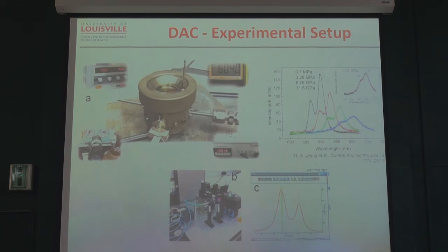Yeah, so this is the experimental setup we have in our lab. So this is a diamond anvil cell. To measure the pressure, you have to use something called a ruby crystal. Ruby has the photoluminescence peak. Under pressure that peak shifts, so from that you can calibrate your real pressure.